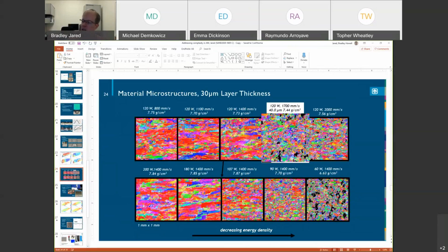Oh, I know what it was. The other thing is a lot of the distribution is actually going back to the surface effect. From what we've seen, internal voids, until they become really large, and on the right side of here you see some large ones, most of the failure we've seen in these parts, if we don't have large voids on the inside, most of it is actually at the surface. And so the surface finish is actually critically important. I don't have a slide here, but I've got some results that show if you take off the surface, you machine it or polish it or whatever, you can get much better effective properties, right? So it's not really the bulk property you're changing, it's the structural property of the member, of the part. The bulk properties are still what they are. And so those are all things you have to consider. So surface finish can be as big a driver as process settings in some of these types of things.